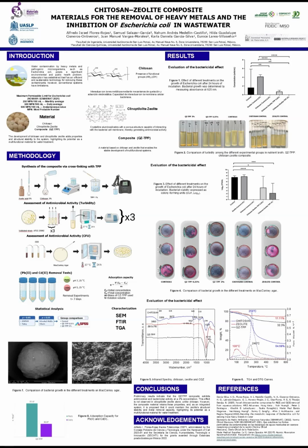The bactericidal activity of chitosan has been extensively documented and is attributed to the protonation of its amino groups in slightly acidic media, which confers a positive charge capable of electrostatically interacting with the lipopolysaccharides and phospholipids of the outer membrane of gram-negative bacteria. This interaction alters the permeability of the cell membrane, promotes the loss of intracellular components, and inhibits bacterial growth. Furthermore, the antimicrobial efficacy of chitosan depends on factors such as its concentration, molecular weight, and degree of deacetylation, which determine the intensity of the interaction between the polymer and the bacterial surface.